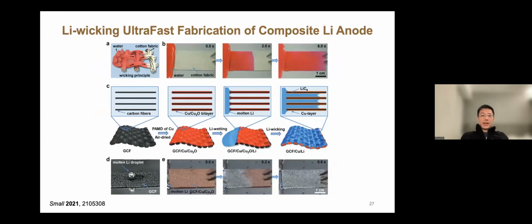Apart from that, we are also quite concerned about how you can really do that in a large quantity, and we have been challenged by our community a lot. They say that for this kind of applied research, if you really want to make a flexible battery, you need to coat it in a very fast way. For graphite or silicon anodes, we can always do the same slurry coating. That's no problem. But with lithium metal, the coating nowadays uses electrochemical deposition, and it takes hours. We can do some melting, but that takes tens of minutes